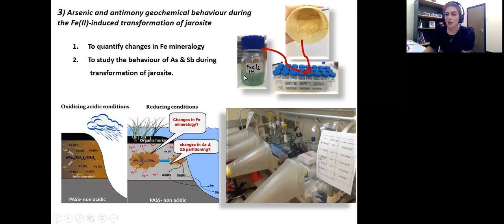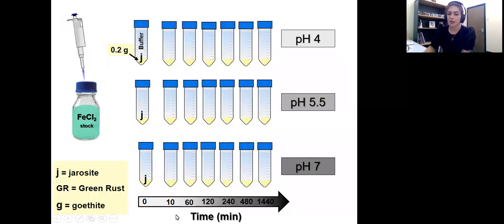And I wanted to see, if we have these conditions and we have different concentrations of iron 2, what will happen to our mineral, which in my case was jarosite in this study. And if jarosite transforms to other minerals, what will happen to arsenic and antimony, which were initially locked inside the structure? So I conducted my experiment inside the anaerobic chamber, and I took my samples in the time intervals that you can see here in this slide.